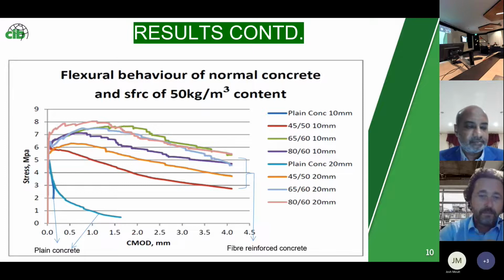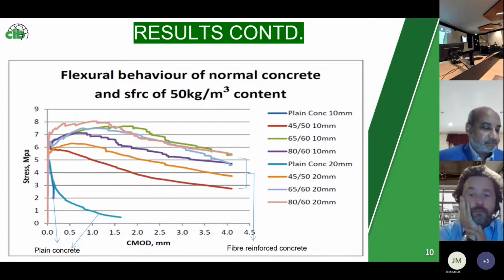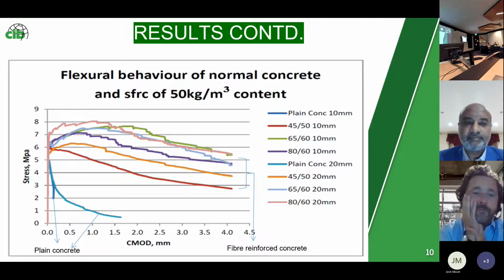And this is the flexural behavior of normal concrete and steel fiber reinforced concrete. You can see from there that we have the plain concrete, and you can see the brittle effect. After the initial crack, that's the end, everything came down. Where we have all those materials with steel fibers, it continued even after the cracking. We have the post-cracking capacity, the strain hardening of the concrete. We're able to carry more load than the load that caused the initial crack. And we could see the results from this side, the length 80, 60, having the highest post-cracking capacity before they came to the end where they failed. They could still carry more load at that end.